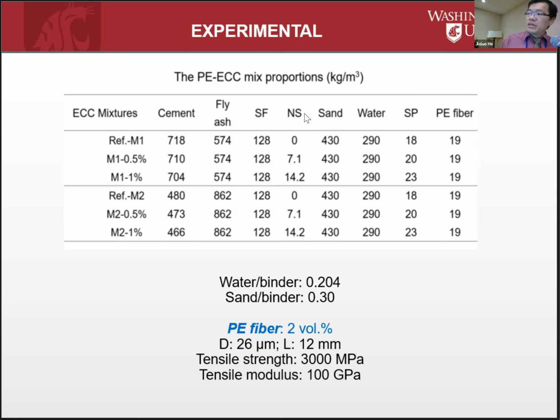One thing you'll see is you'll end up with really high strength. Usually, you will see 28-day compressive strength more than 75 megapascal because the water binder ratio is relatively low, 0.204. And the PE fiber was added at 2% by volume. And this is a PE fiber, again, finer than your hair because the diameter is 26 microns and the length is 12 millimeter. Again, if we were to optimize the performance, we can play with the aspect ratio of the fibers. Like longer fibers may give you better results.